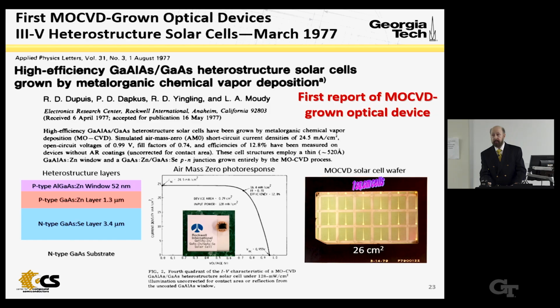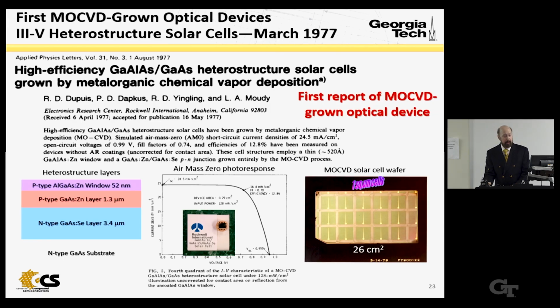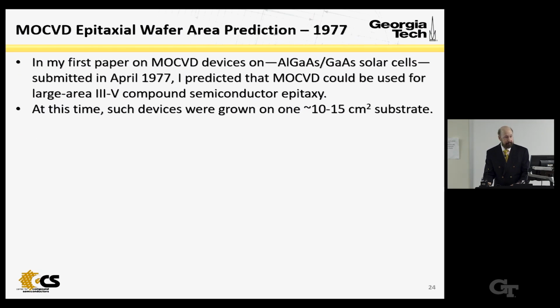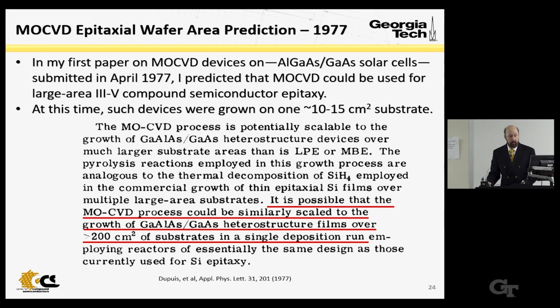So this is the first report of an MOCVD grown optical device. At almost the same time, LPE was being used for AlGaAs solar cells, and they were limited to maybe 1 or 2 smaller pieces, maybe 1 inch square in the LPE boat. So in 1977, when I published this paper, most of these devices were grown on 10 to 15 square centimeter substrates, and in my paper I predicted that this would be scalable by MOCVD to over 200 square centimeters of substrates in a single run.